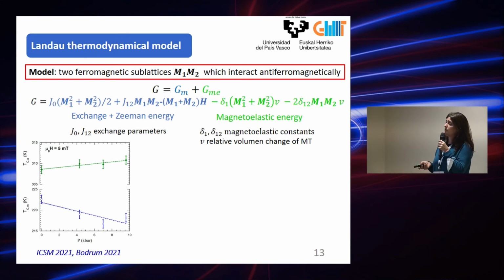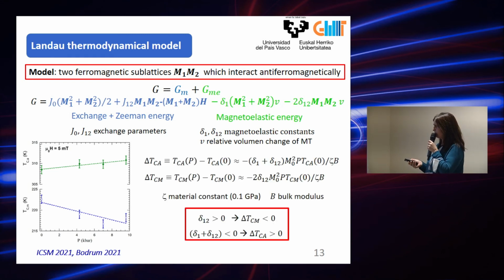Okay, to explain this, we also try to give a model based on this Landau thermodynamical theory, and for this we suppose that the system is composed of two ferromagnetic sublattices with two different moments, and that these two ferromagnetic sublattices interact between them antiferromagnetically. To evaluate this theory, we take into account this energy, with two terms, one related to the exchange energy and Zeeman energy, and another term related to the magnetoelastic energy. So this model allows us to evaluate this magnetovolume effect that can occur in these materials.